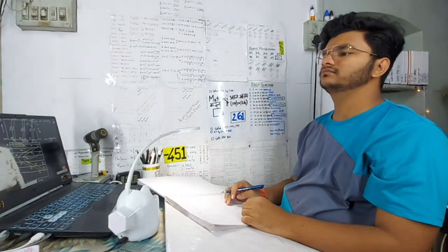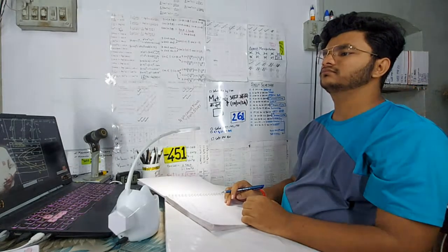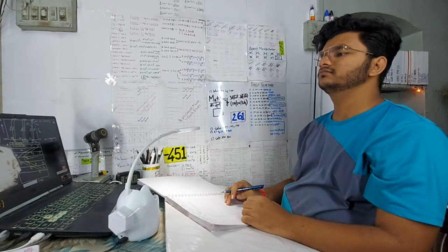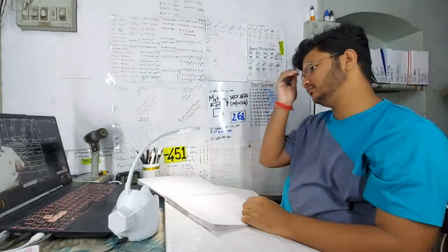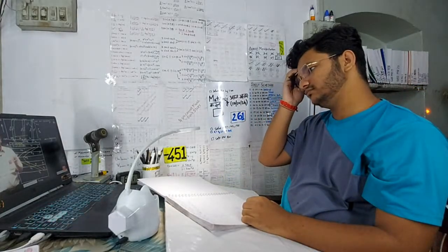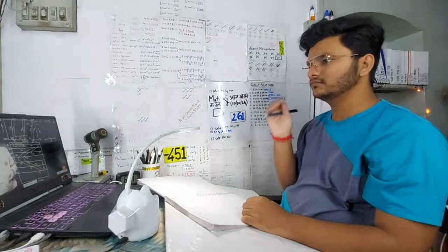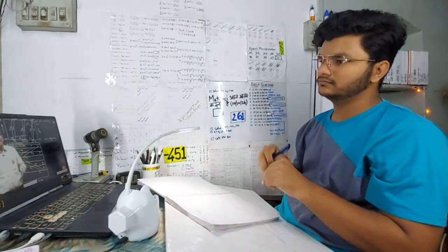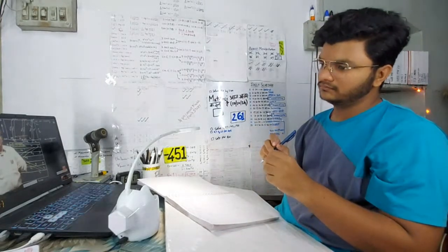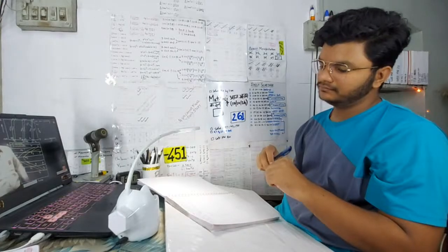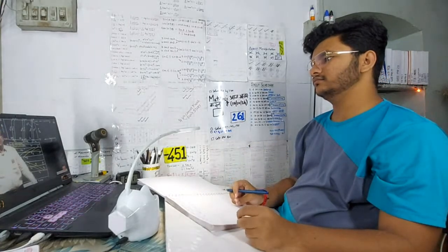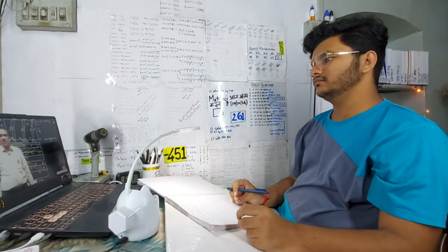You have to say, Martensite formation is not by diffusion. Yesterday we studied Martensite formation characteristics. Austenite to Martensite transformation characteristics were studied. What was written there? Martensite formation is by a diffusionless process. Correct? So it does not happen by diffusion. It does not depend upon time. It is by a diffusionless process, as already stated.